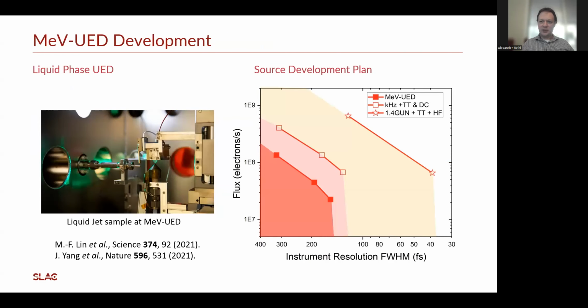So finally, I just wanted to give you a flavor of the outlook on this instrument, and we're very committed to the continual development of our instrument here at SLAC. We're preparing currently for a second liquid phase run with a liquid sample environment, which will occur in the middle of 2024. Here, a thin film liquid jet can be probed using the MeV-UED can start to look at those liquid structure dynamics, both statically and with an optical pump.